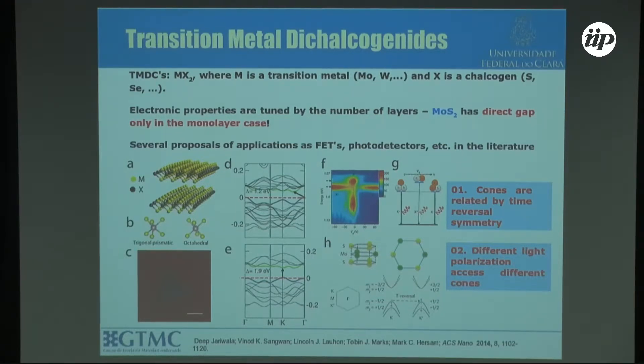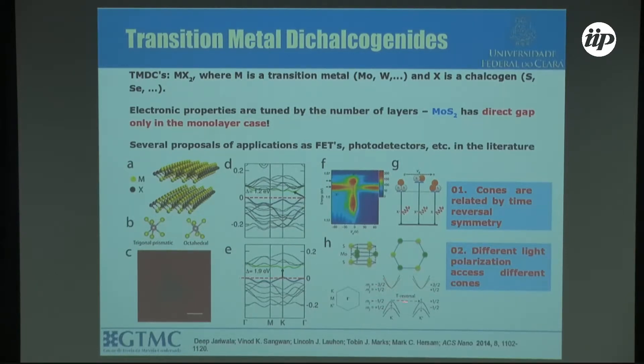If you have light polarized in one direction or the other, you access a state that has certain magnetic moment features, and in the other cone the magnetic moment is reversed. That's how you can see something like valleytronics in the system — you can access energies related only to one cone or the other, and they behave differently under a magnetic field. So what I'm going to discuss is the Zeeman effect and diamagnetic shift for excitons in transition metal dichalcogenides.